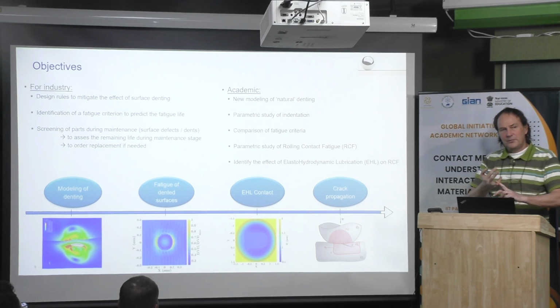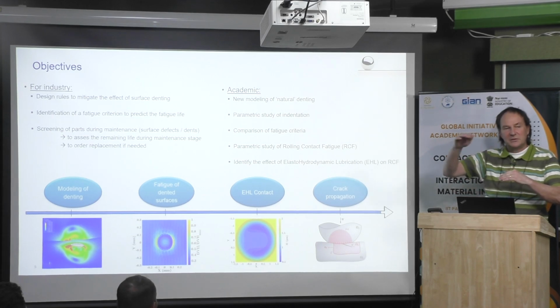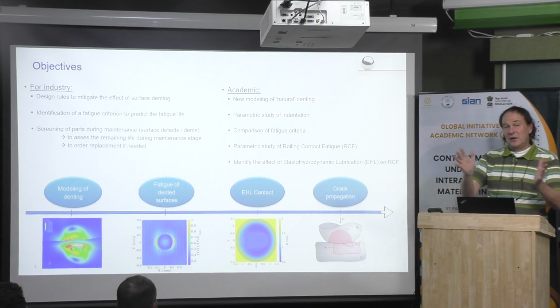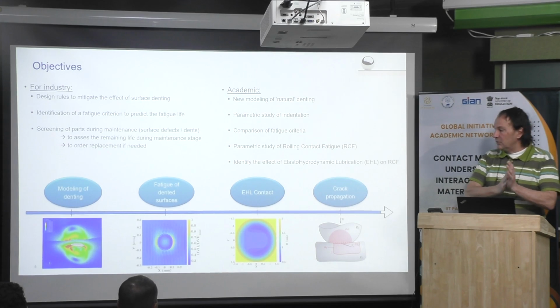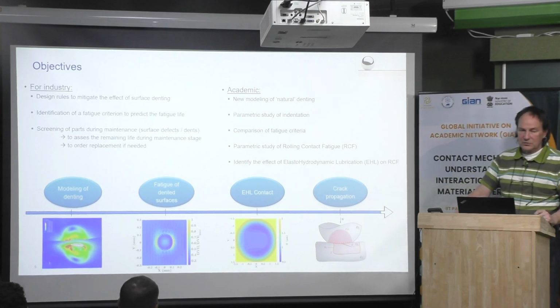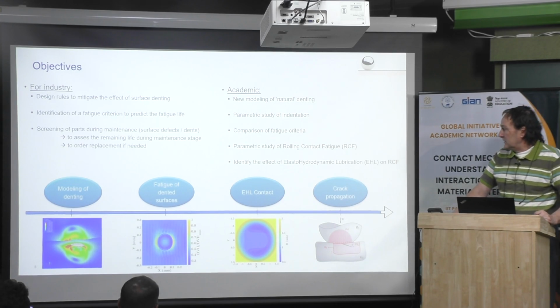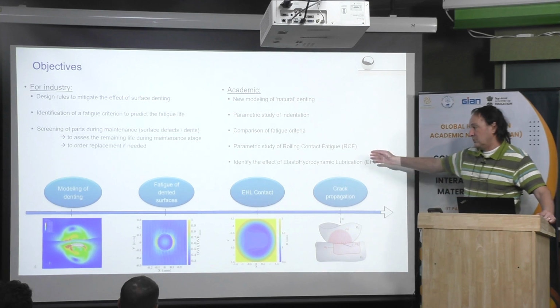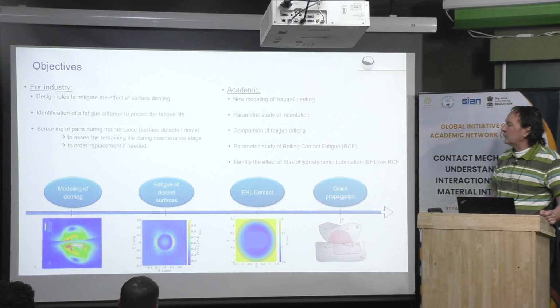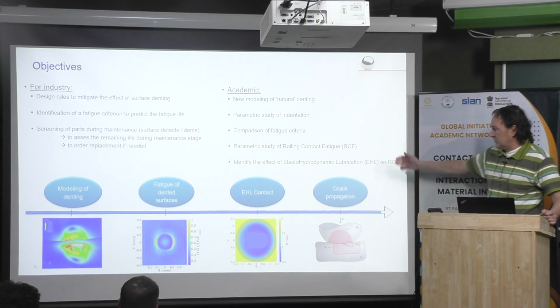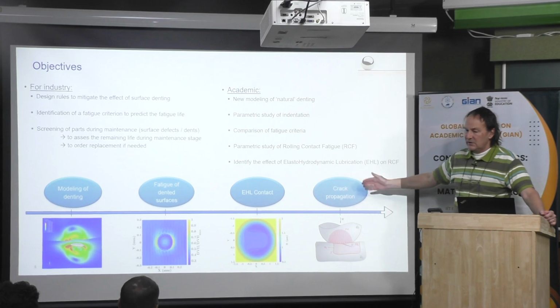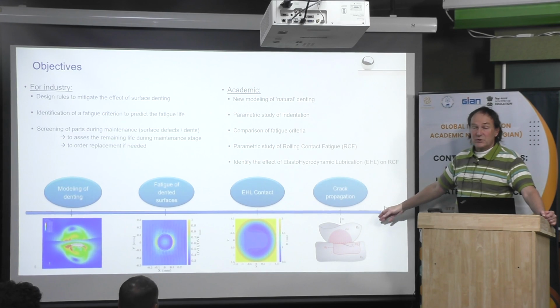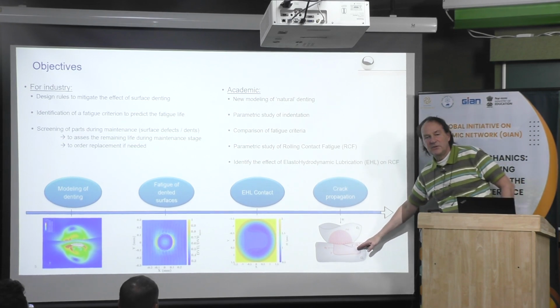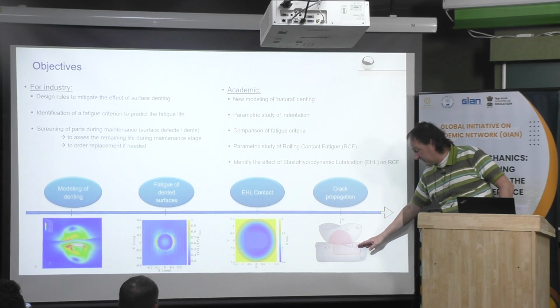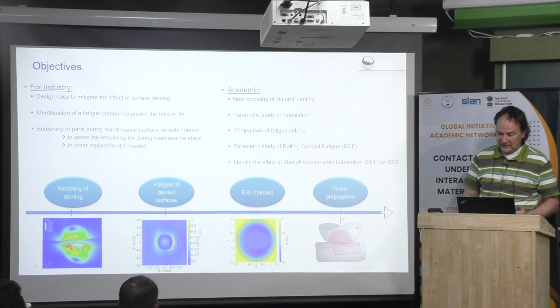And you can use ALE, arbitrary Lagrangian-Eulerian, but you need to update the geometry every 10 time steps. And even with that, it can crash when you have a large deformation, large strain. Then the optimum for that was to use a CEL approach. With that it was possible to compare different criteria for rolling contact fatigue, and also to see the effect of EHL. And we also did more things. For example, we investigated the effect of residual stresses, because the surface is treated with a thermochemical treatment, and the surface is hardened, in fact.